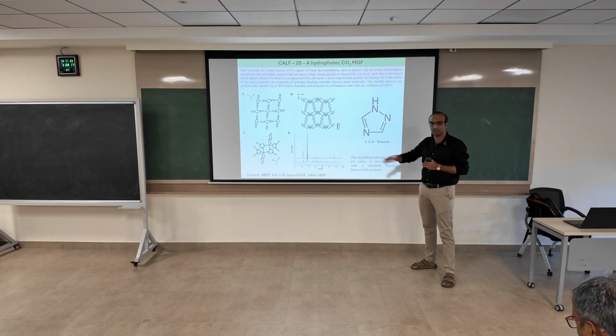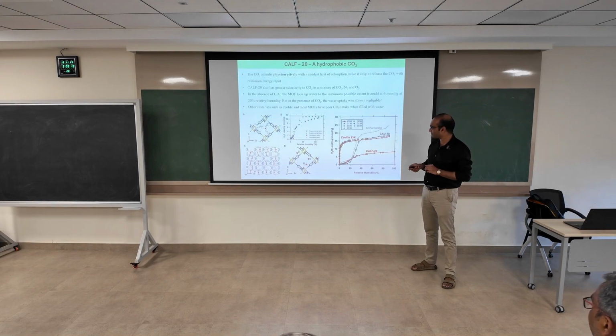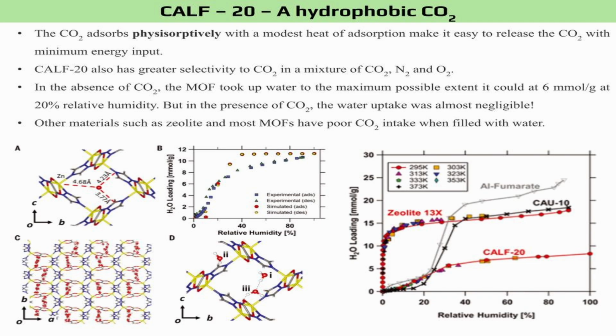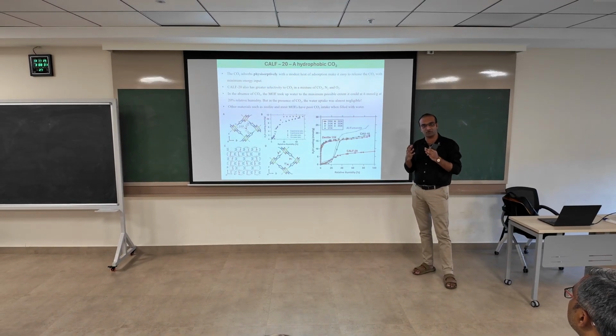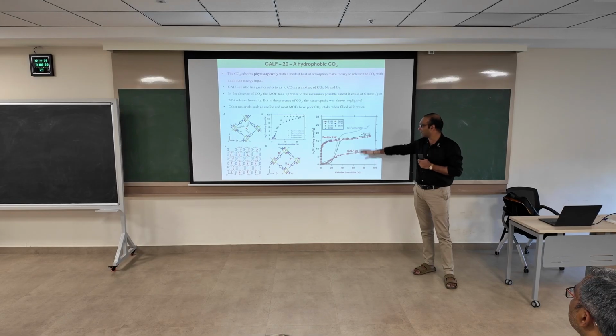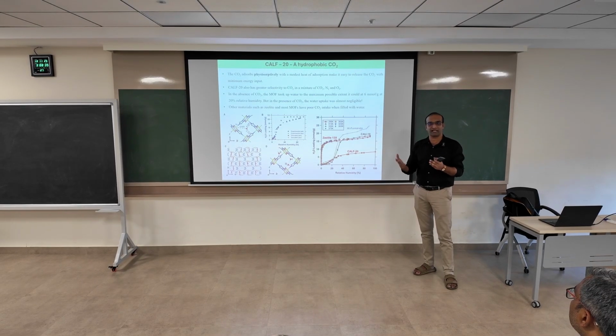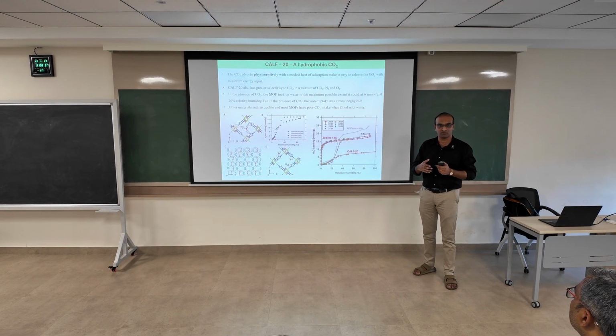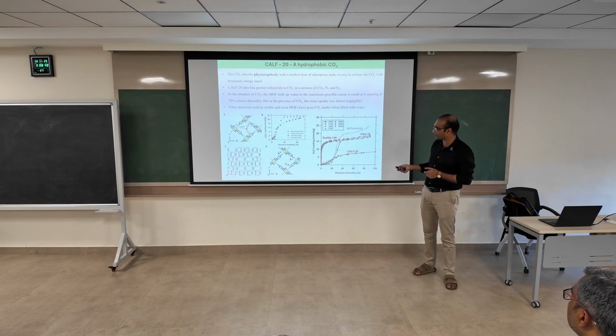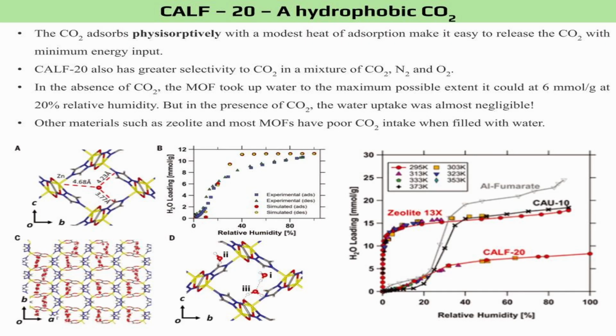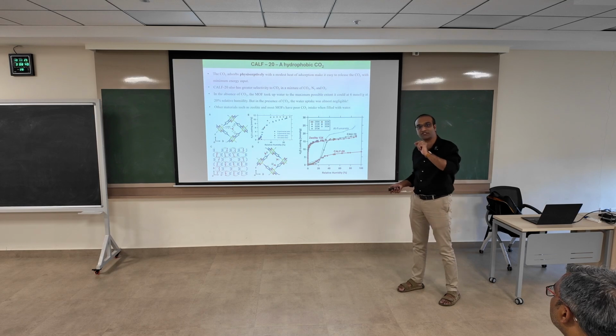And most of these MOFs, even zeolites, okay? If you subject them to all the previously known MOFs, Al fumarate and zeolite 13X and CaU10, all these are well-known MOFs for CO2 capture. If the gas that's coming out has a large amount of humidity, a large amount of water, it will stop performing. It will not capture CO2, it will preferentially capture your water, okay? But this particular MOF had an ability to capture at least up to 40% humidity, in 20% humidity, it was still capturing preferentially only CO2.